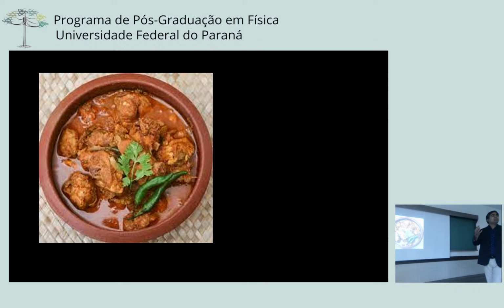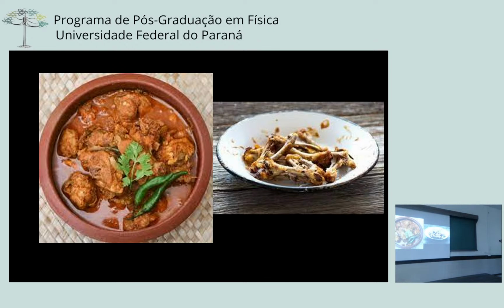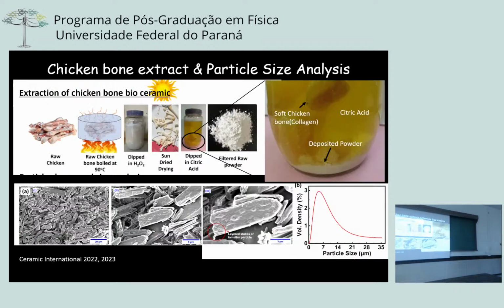Now the question is, can we take something from nature and build some green material which can replace hydroxyapatite? So what we do, this is chicken curry, right? Out of chicken, you order them. If you take chicken, what you dump is this object. The bones, you throw them, right? Now what we do here is, you take this chicken bone and put it into certain simple chemicals. For example, we put it into H2O2 and then citric acid. Again, both of them you use in your household. Put them together here in a jar. If you dump it, what you see after a certain time, depending on your concentration, you see a white powder collected. What is this white powder?